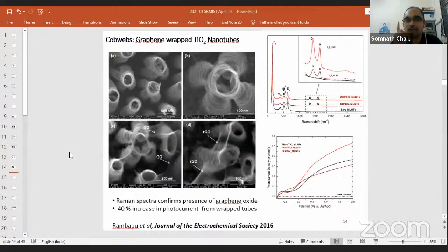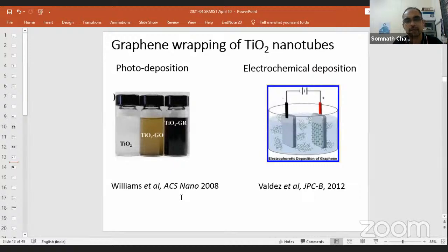So the first innovation we made was to carefully craft our anodization process, where we made the electrolyte in a way that it had lower surface tension forces. So the nanotubes fabricated, as you can see in the top one, were separated, so there is plenty of space around the nanotube for the graphene to go around. Then we ran the graphene deposition. There were two techniques by which we tried graphene deposition: one was photochemical deposition, one was electrochemical deposition.